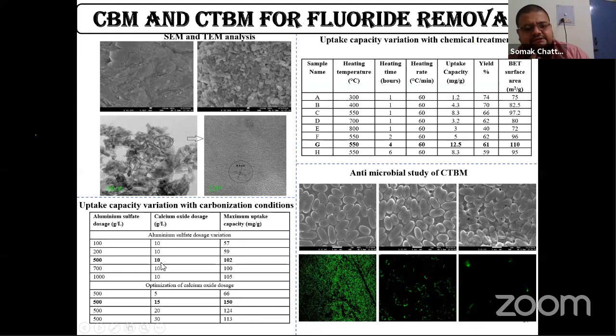The calcium oxide dosage was kept fixed, but when we got to 500 gram per liter of aluminum sulfate dosage, we fixed it at 500 and then went for calcium oxide dosage variation. And finally, we were able to achieve an uptake capacity of 150 milligram per gram. Now, this 150 milligram per gram is the highest capacity for any type of natural adsorbents which are present for fluoride removal.